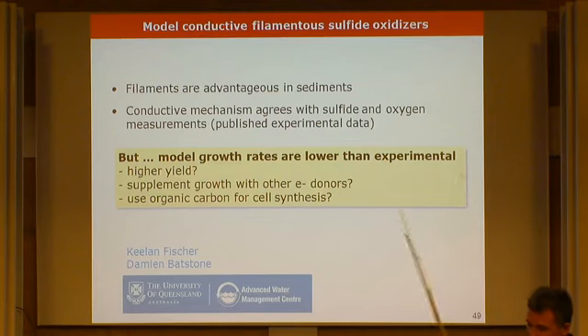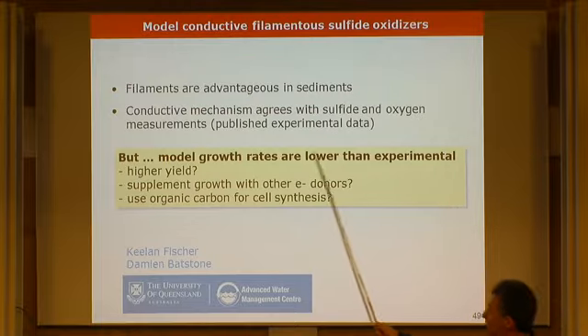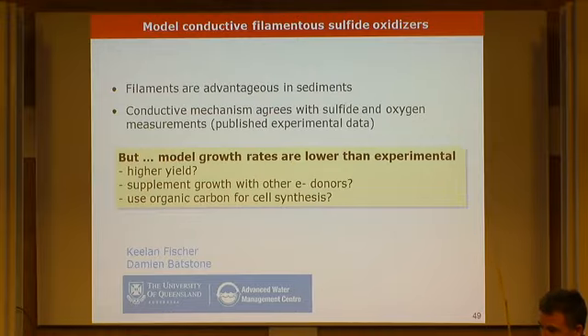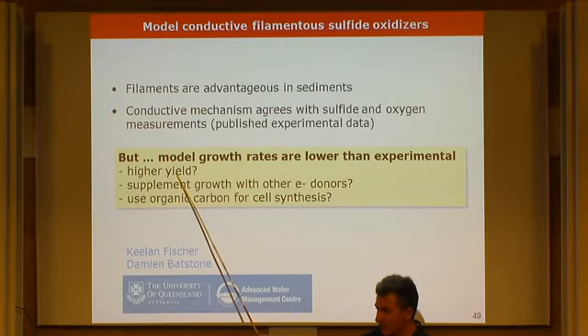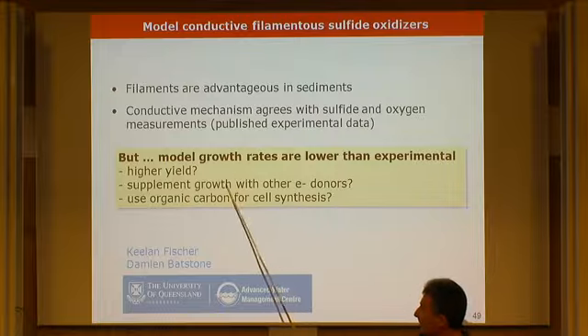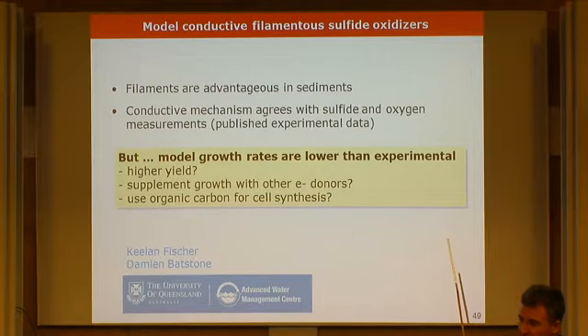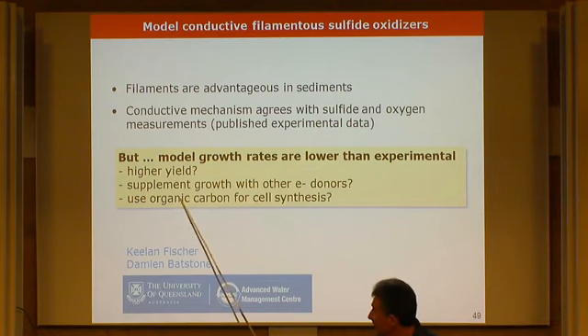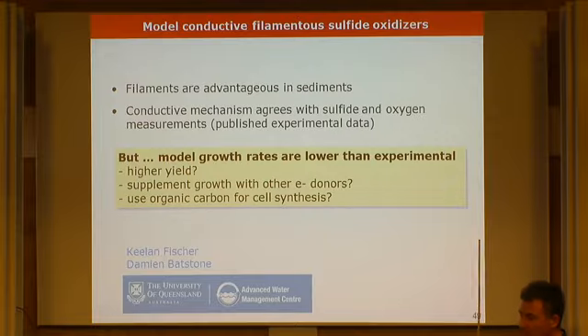There is one more thing. So we can somehow explain the concentration profiles, but the growth rates that we calculate are about 3 or 4 times lower than observed experimentally, which means that the cells either have a higher yield for whatever reason, or they supplement their growth with other electron donor. So it's not only the sulfide, but maybe they can take iron or whatever. And it also means that there may be organic carbon involved here. It's not only autotrophic. Maybe they can grow in a heterotrophic way.